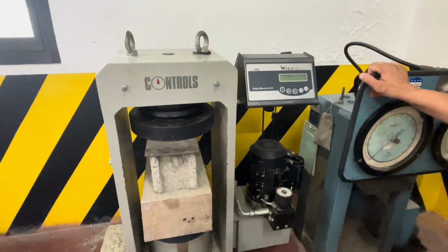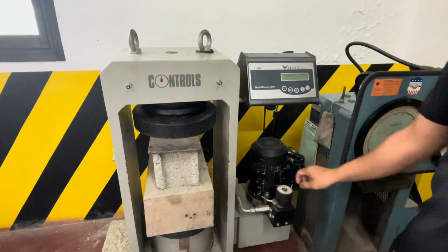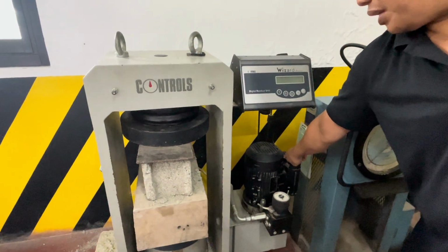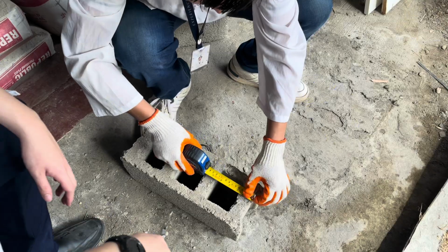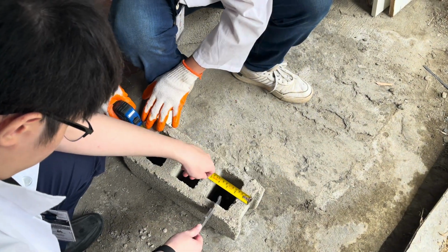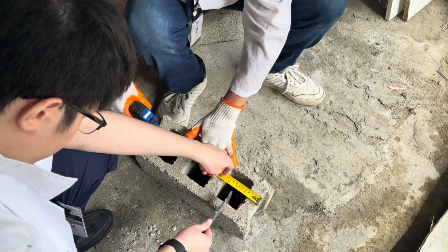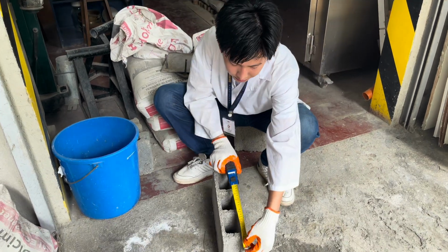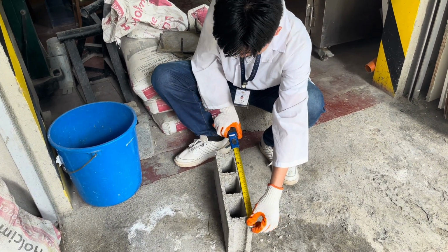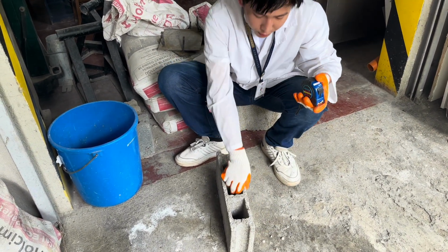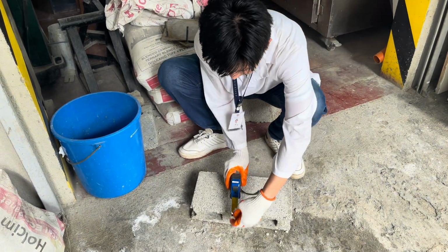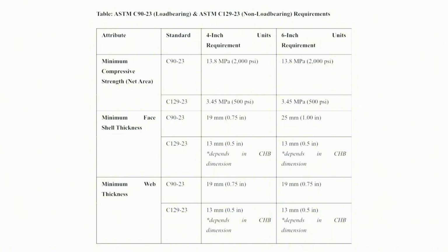The percentage errors of experimental values were 18.60% and 29.7% for 4-inch CHB and 6-inch CHB respectively, signifying moderate departure from theoretical values. In summary, though the CHBs were partially compliant with dimensional requirements, their compressive strength tests reveal that they are not fit for load-bearing use in construction projects. The results highlight the importance of enhanced manufacturing processes and quality control to conform to industry requirements and guarantee safe use in construction works.